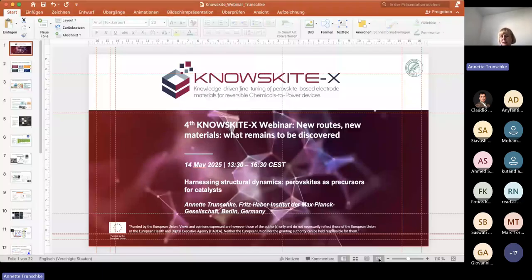And we can also do depth profiling, and more important, since we generate such a high amount of electrons in this experiment, we can also do measurements in presence of the reactants, so ambient pressure XPS. And so we did this also with these perovskites and investigated the surface of the perovskite in presence of propane and oxygen.